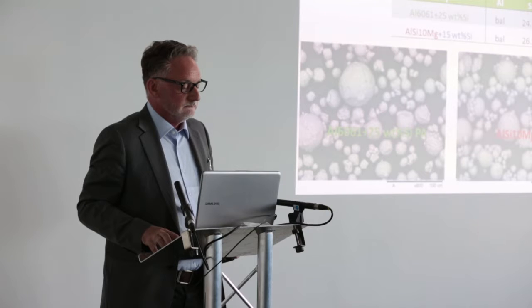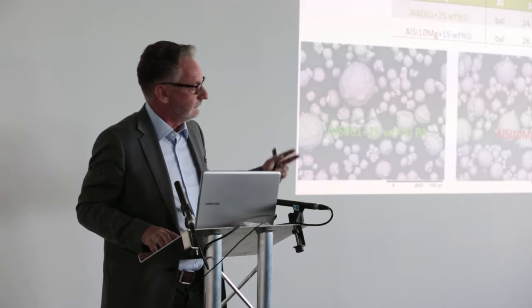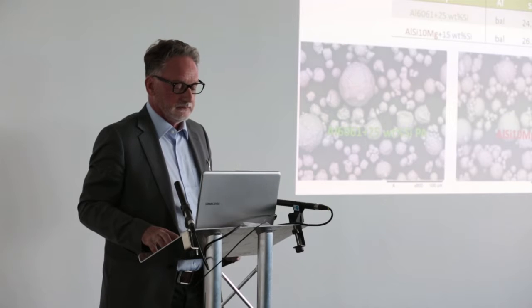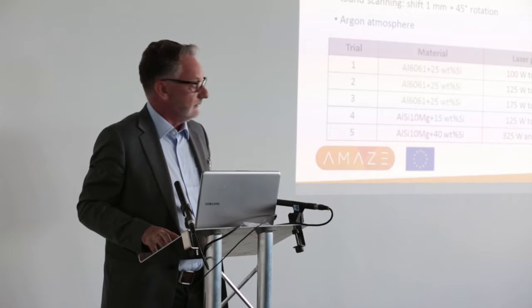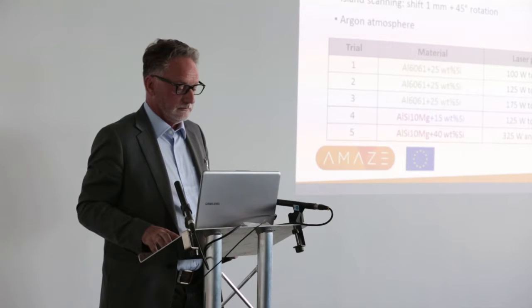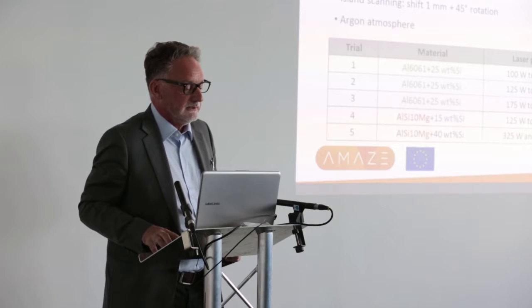The powders were obviously analyzed for chemistry and so on, and we looked at the morphology, and you can see all the powders are nice spherical materials, which made them very suitable for the processing, and they were blended in the case of the aluminium silicon with extra silicon. And we did a series of trials on our Concept machine.